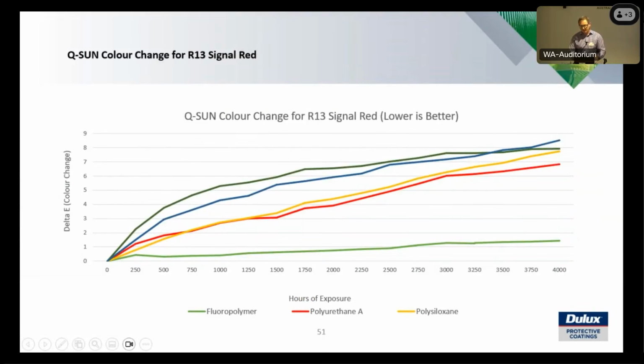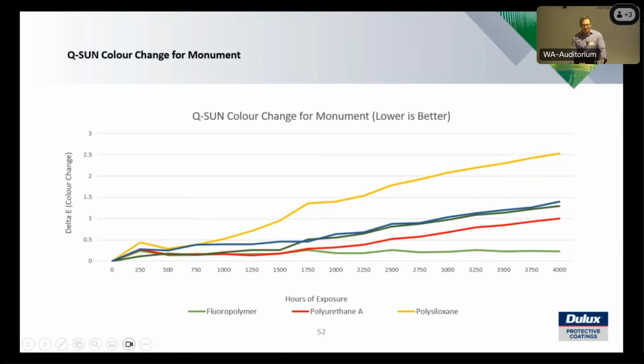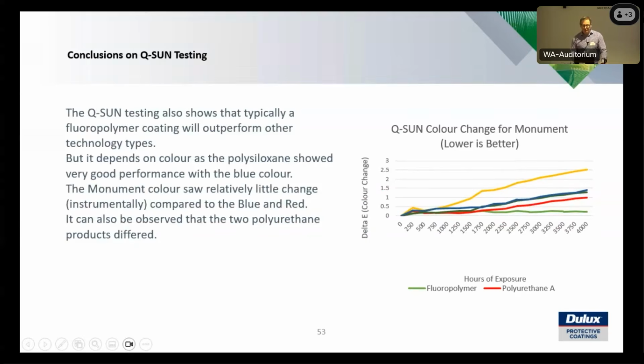Again, you're getting some mixed results with the other coatings, so there's no real consistency as to first, second, third, fourth as the better coating system. And the Monument, the fluoropolymer is pretty level all the way through. Funny enough, the siloxane provided not as good a test on that one, where visually it didn't look too bad. So the conclusions on the Q-Sun: typically the fluoropolymer coating will outperform other technology types, but the colour plays an important role, as drastic change is seen in blue and red, but less in the Monument as well.